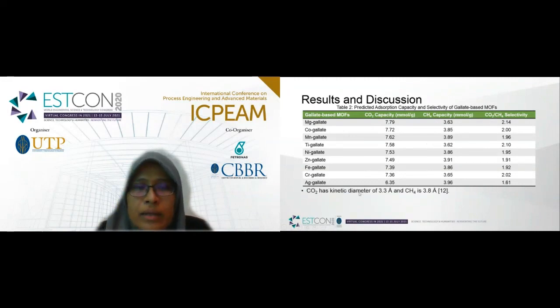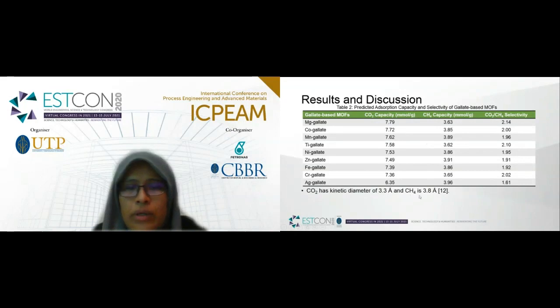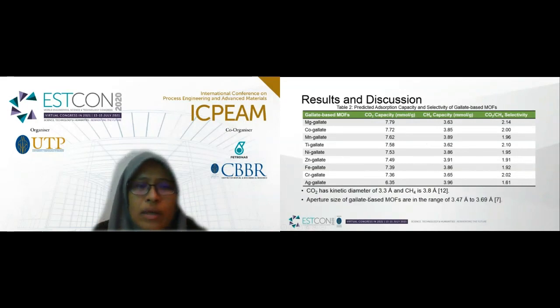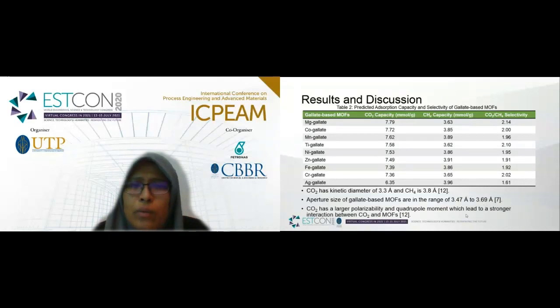CO2 has a kinetic diameter of 3.3 angstrom and CH4 is 3.8 angstrom. The pore aperture size of gallate-based MOF is in the range of 3.47 angstrom to 3.69 angstrom. Therefore, gallate-based MOF is theoretically capable of selectively capturing CO2 from a CO2-CH4 mixture based on the size differentiation. Furthermore, CO2 has a larger polarizability and quadrupole moment, which lead to a stronger interaction between CO2 and MOF. The highest predicted capacity is achieved by Mg-gallate with 7.79 millimole per gram, and the lowest is achieved by Ag-gallate with 6.35 millimole per gram.